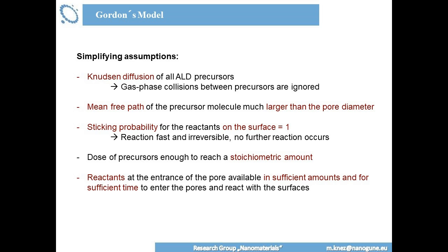Of course, all of this is simplification. That means you will never get a really valid value in terms of numbers. But it will give you an idea of how much time you really need, on the order of magnitude. So the sticking probability is 1. The dose of the precursors is enough to reach the stoichiometric amount. This is what you always need to have in terms of ALD processes. You want to have a minimum of molecules to have a full saturation of the surface. Otherwise, you have an undersaturated process. So that's all usually valid for all ALD processes.